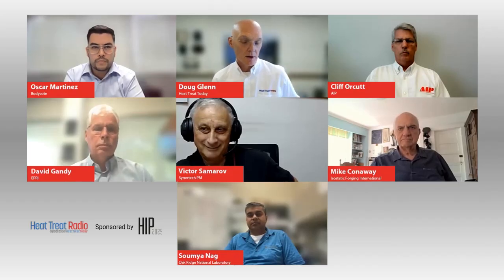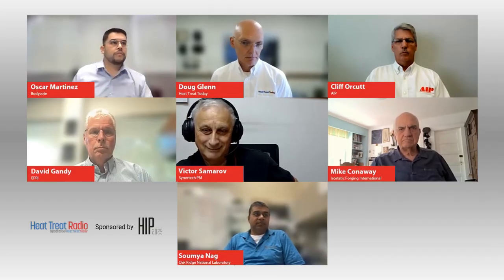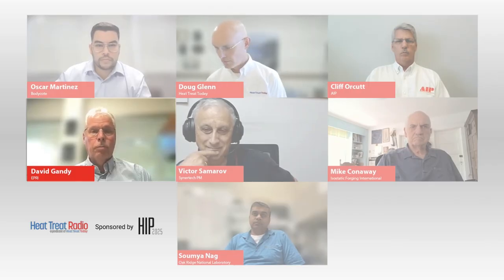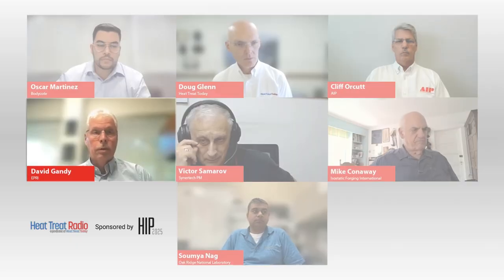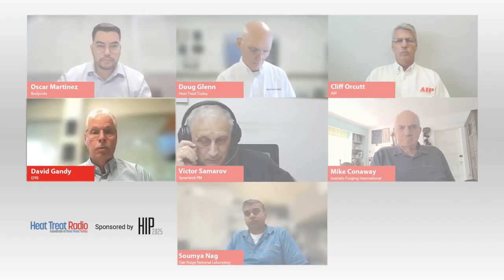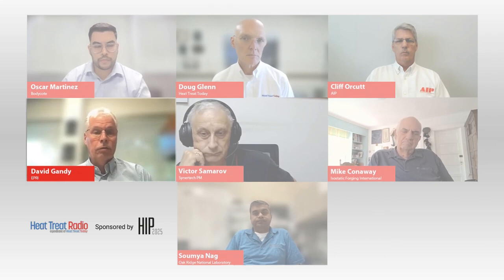So maybe Dave, you can chime in a little bit. Dave, any thoughts on the powder to part challenges or opportunities? Another question I've got here is what appears to be the most promising avenue to take to bring it about? Well, I think one of the things that you've really got to consider for powders is powder cleanliness. We've worked quite a number of years on trying to reduce things like oxygen in the powder, so that as you consolidate that component, you don't end up with oxides that are trapped at the grain boundaries or prior particle boundaries. So it's very important that we get powder manufacturers to work with us to bring the technology forward. In addition to that, though, if we start making very large parts in a 4-meter unit, we're going to have to really scale up our powder production capabilities in the U.S. And quite frankly, that's not happened at this point.